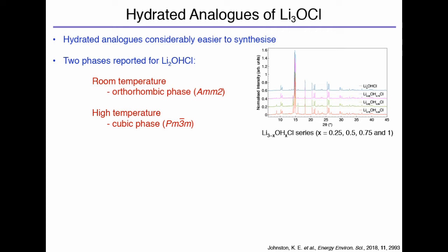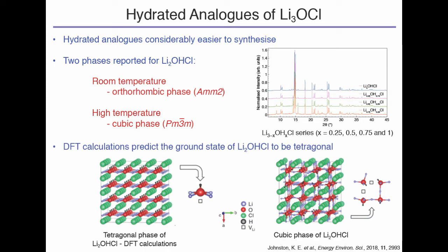Now, because this was a collaborative effort with Seifel and James, we decided to do some DFT calculations to try and predict the ground state, so the lowest possible energy conformation of this material. And what we found was that the ground state for Li2OHCl was actually a tetragonal phase, not orthorhombic. And you don't need to worry about what that means, but in this particular structure, it looked like all of the OH groups were aligned along one particular axis, along the A direction. And that was in total contrast to the high temperature phase, where the OH groups appear to be totally randomly oriented within the structure. So what's causing these differences?